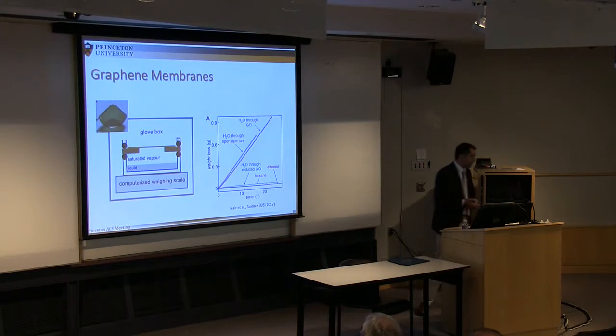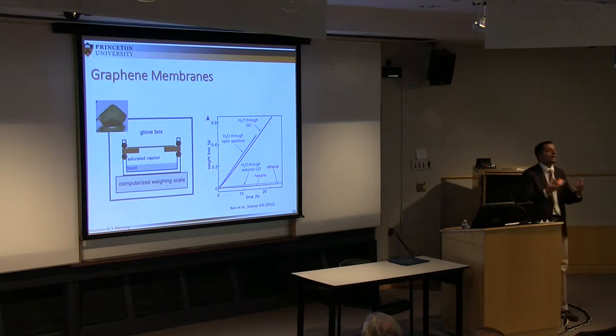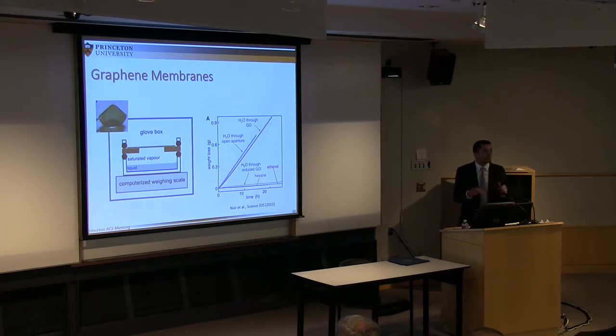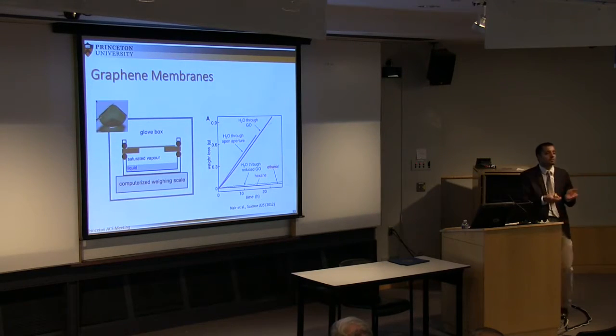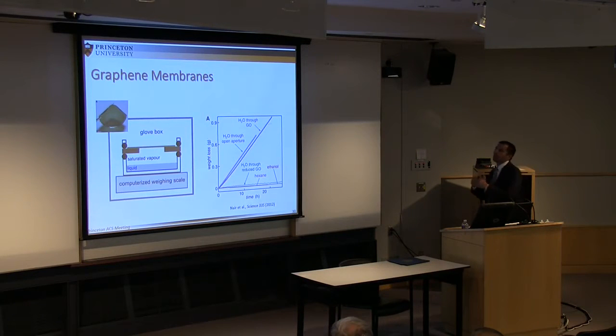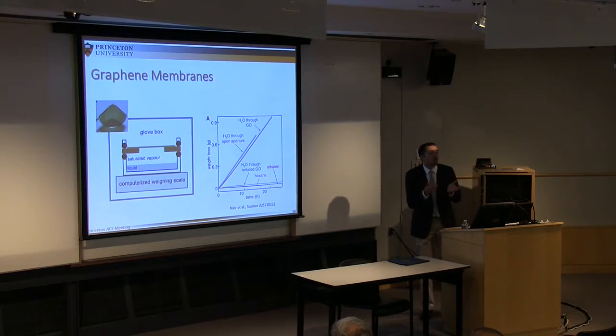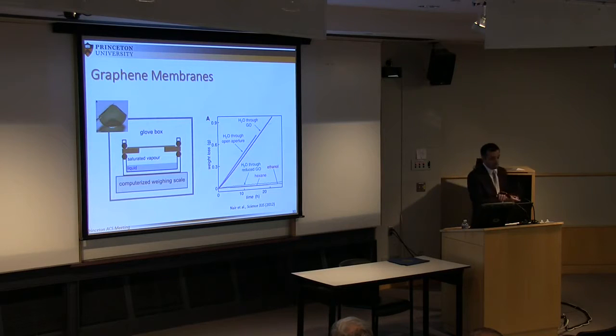Why? Because you don't have, or you have fewer of these functional groups now between the basal planes of your graphene film. So this film, just to clarify, is not one graphene sheet, it's many sheets on top of each other. But they have functional groups which are compatible with water, which is why it's hydrophilic. So if you get rid of some of these functional groups, you see that you can indeed now have a selective filtration.